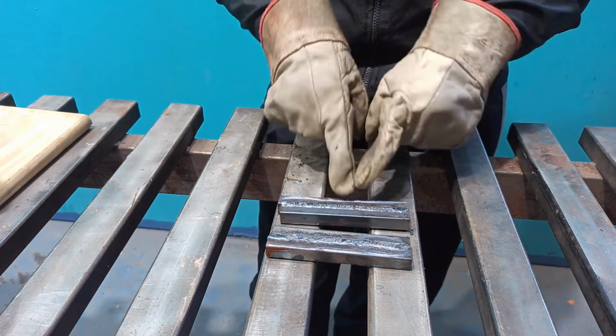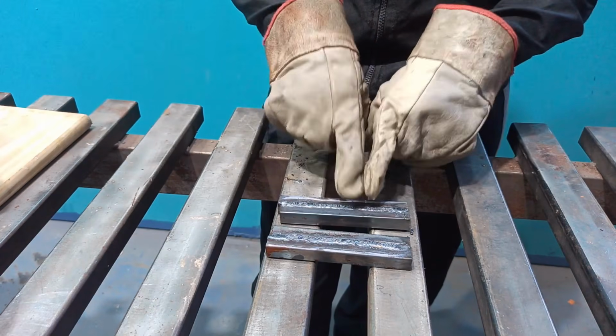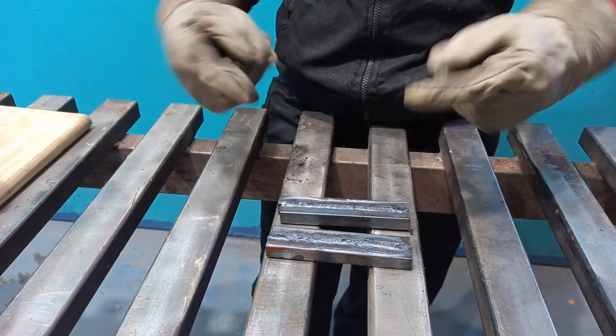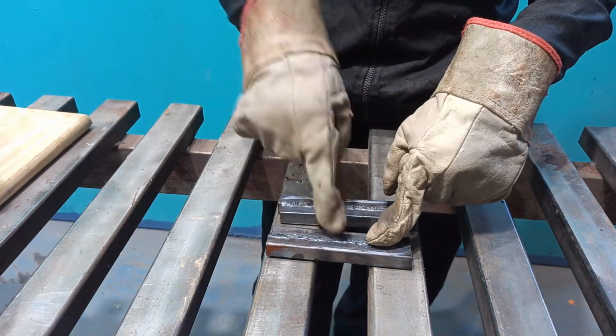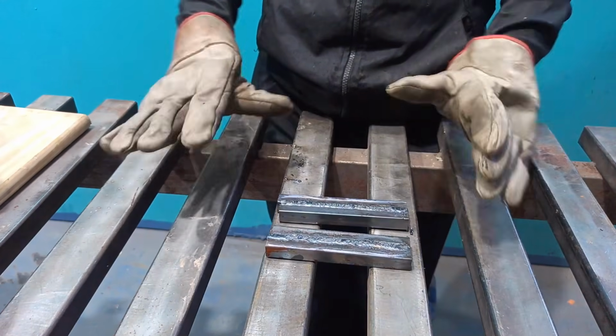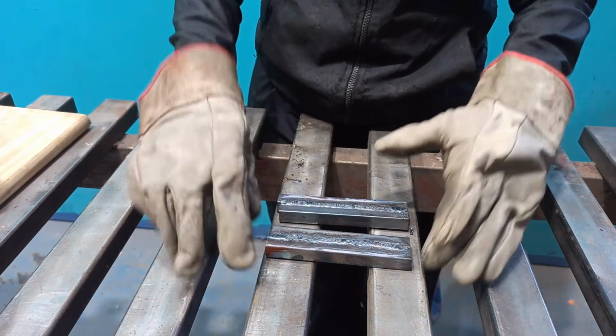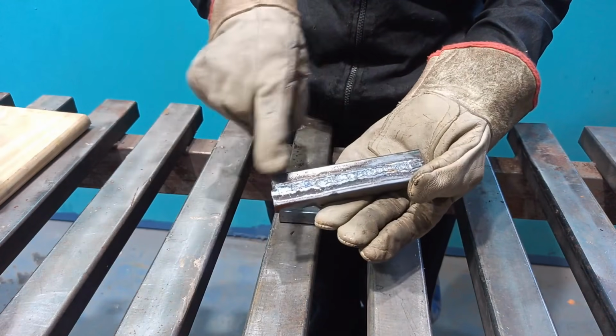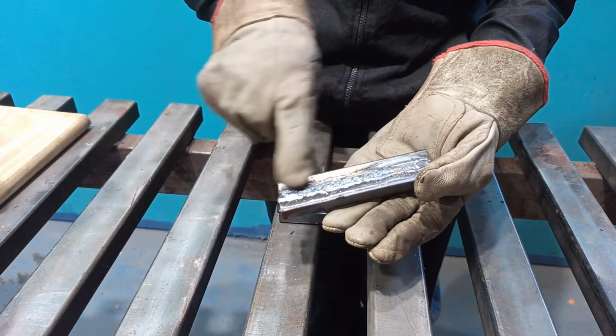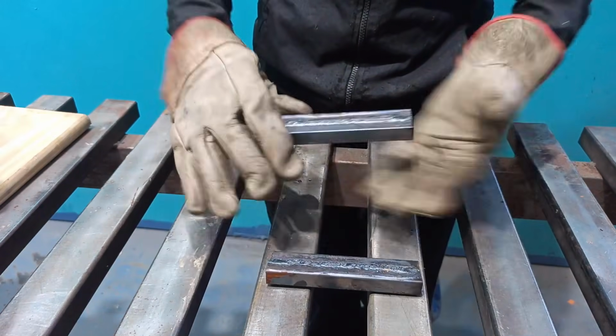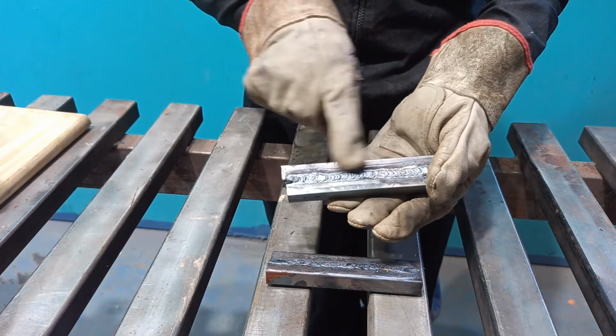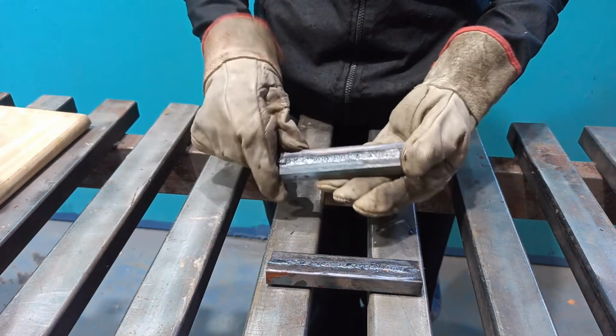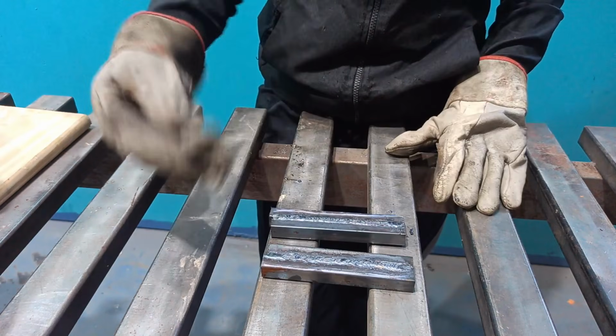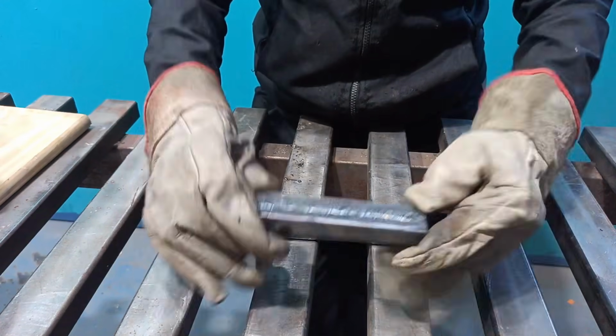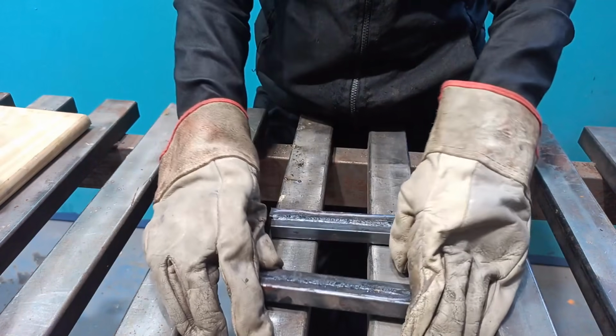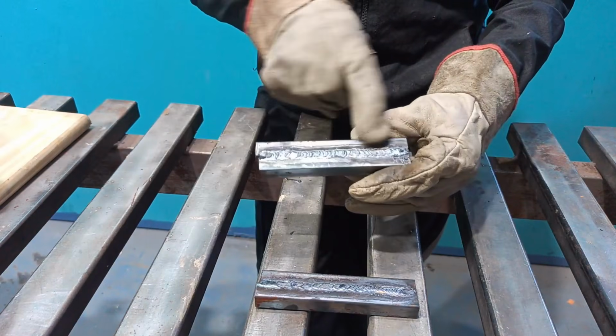As you can see, with reverse polarity, I didn't even have to hit it or anything to remove the slag. It just came off by sliding it. However, with straight polarity, I had to hit it to get the slag off. Another difference we can see is that, for example, with straight polarity, the bead penetrated deeper into the material. And with reverse polarity, it was more raised, like a mountain on the material. This means that with straight polarity, we will have more penetration into the material than with reverse polarity. We will have less penetration into the material.